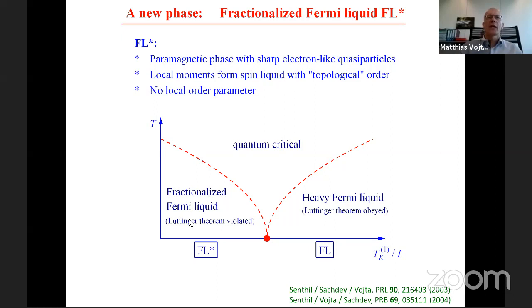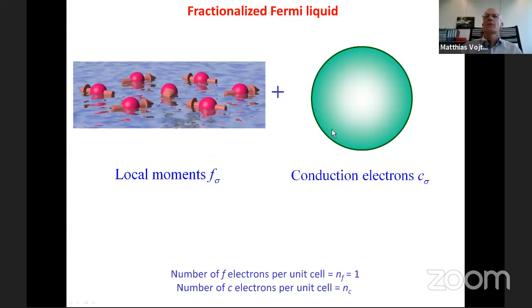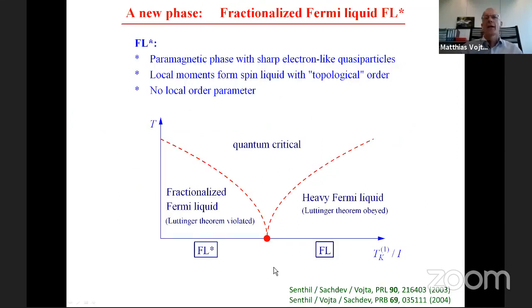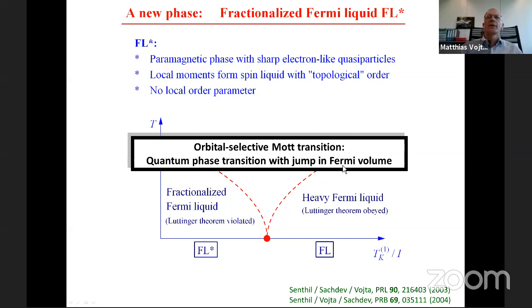This has signatures both of a fractionalized spin liquid, and that's written up here. The local moments form a spin liquid, which can have topological properties. There's no symmetry breaking, no order parameter, but it also has sharp electron-like quasiparticles, which come from the subsystem on the right-hand side. That means that in this phase, Luttinger's theorem is violated because the Fermi surface will only come from the c electrons and will not involve these local moment electrons. But that's an interesting phase diagram because it has a quantum critical point, or let's say a quantum phase transition between these two phases, but there is no symmetry breaking, but there is a jump in the Fermi volume. And what happens essentially is that these local moment electrons are itinerant on the right-hand side and are localized on the left-hand side. Therefore, people also like to call this an orbital selective Mott transition.